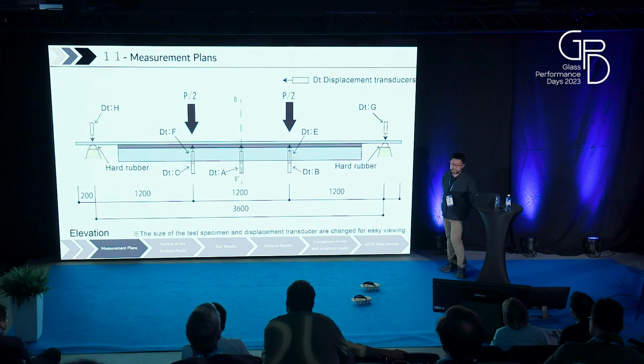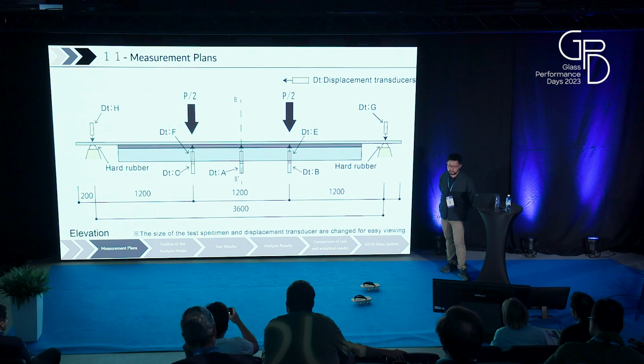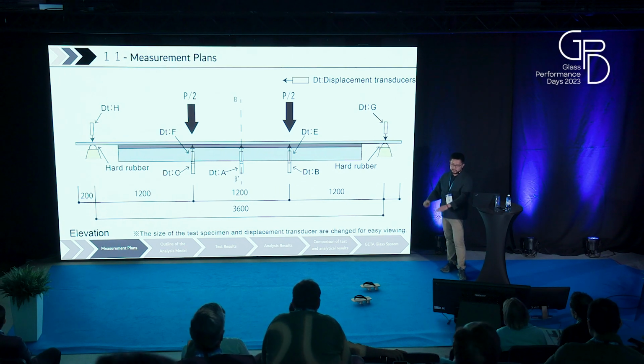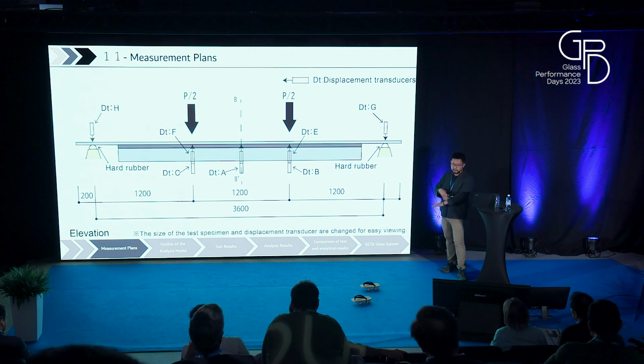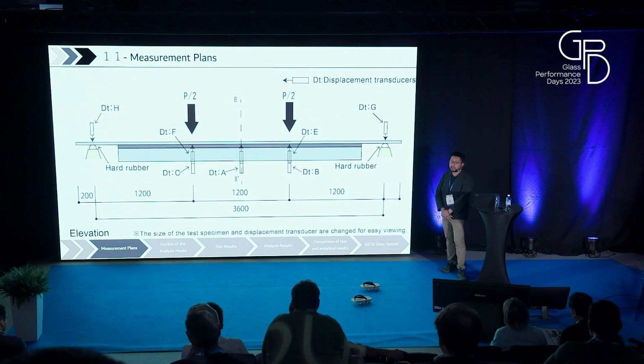Okay, to prevent the specimen from being damaged at the point of contact with the testing machine, hard rubber of 3 millimeters thickness was placed between the flat glass plate and the force application area, and between the flat glass plates and the support points.